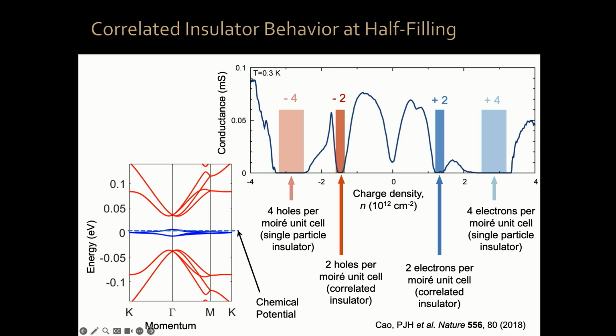And the next interesting thing that happened is that, by the way, this behavior only happens if the twist angle between the 2 graphene sheets is very close to 1.1 degrees. More or less 1.1 plus or minus 0.1 degree. 0.9 or 1.3 doesn't work. So it's very specific to the presence of those flat bands, to that magic angle condition.